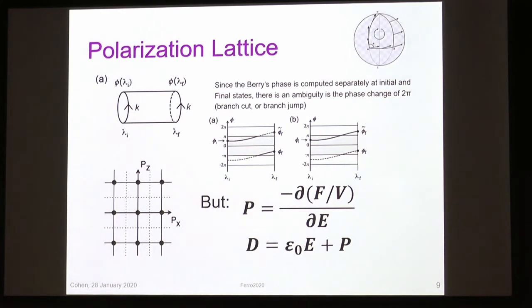So this is the polarization lattice. In a case where the polarization is zero, say in a centrosymmetric crystal. In a polar crystal, what happens is as you vary some parameter, the polarization changes, and you can get the change in polarization as you vary that parameter. That's the fundamental theory of the Berry's phase polarization. So that's fine as long as you follow some path.